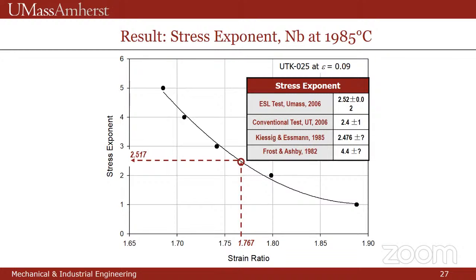We looked at a previous result, which strangely enough also used a rotating sphere, and they got 2.5 also, but didn't do an error analysis. And the last one is kind of interesting. We looked in the creep mechanisms map book compiled by Frost and Ashby, and it says 4.4. So what's going on there? Well, we found the original source paper that they'd cited, and those results were extrapolated from measurements at 1200 C. And so the conclusion is that you have to know all the mechanisms to know whether or not you can extrapolate the measurements. In this case, a design based on extrapolated measurements would work, but it would be too heavy.